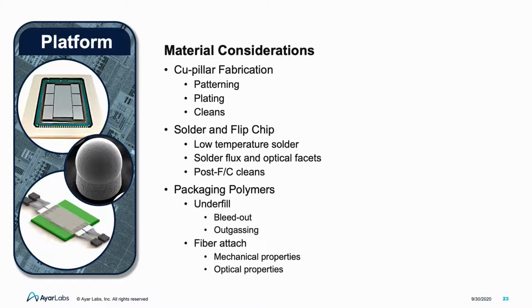For solder and flip chip, MCPs can benefit from low temperature solder, a process that will be explored in more detail later. Fluxless flip chip or effective flux cleans for the optical facet, and potentially any required cleans post flip chip. Finally, regarding the polymer selection, the underfill technology cannot have epoxy bleed out or outgassing that fouls the optics. And any selected polymer must include appropriate optical properties to go along with the traditional mechanical properties.